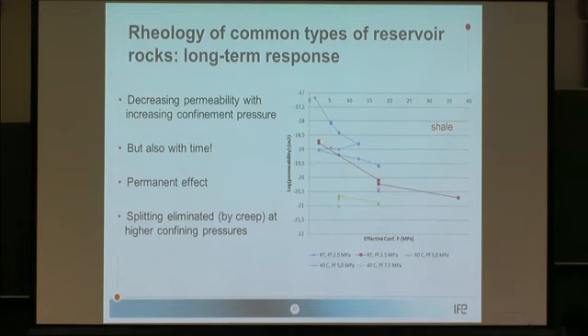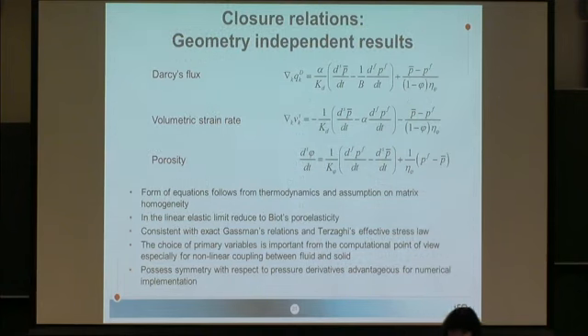So what we found, coming back after several days, is that the permeability had changed. Our permeability actually increased or reduced. And this is under the same load. So clearly, even in the permeability, you can see a time-dependent response, which means you do observe creep in the experiment. So which one is next in time? It decreases, because this is a minus power. You squeeze, and you decrease your permeability. So the data shows that the behavior of rocks on a short time scale is elastoplastic, and when we are interested in the long-term behavior, we have to consider viscous properties, even for sedimentary rocks, typical reservoir rocks.